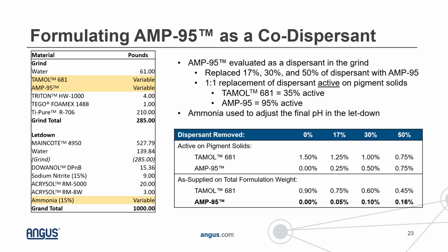And so how we went about taking a look at this formulation is we wanted to evaluate the use of AMP95 as a codispersant in the grind. We looked at replacing 17, 30, and 50% of the existing dispersant with AMP95. And it's really critical, I think, how we did this. We replaced the dispersant active on pigment solids. In this case, our initial dispersant, the Tamol 681, is 35% active. We treated the AMP95 as 95% active. If you look at this on an active on pigment solids basis, down at the table here, our original formulation contained 1.5% of Tamol 681 on pigment solids and no AMP95. If we removed 17% of that dispersant, we are now at 1.25% of the Tamol 681 on pigment solids, and we introduced 0.25% on pigment solids of AMP95. We continued this up to 50% reduction in the primary dispersant.